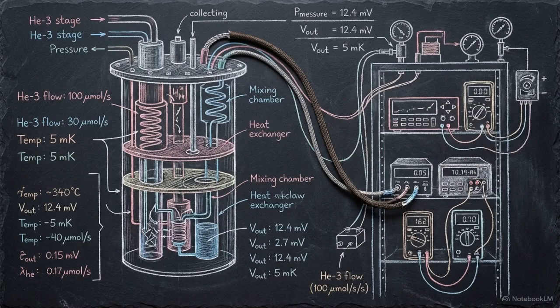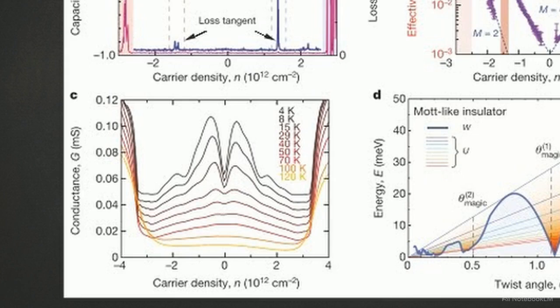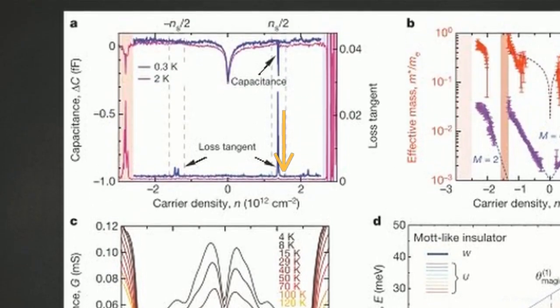Researchers proved this interaction-driven phase exists by measuring the material's response without an external magnetic field. This data shows electrical conductance versus carrier density. Panel C reveals deep valleys in conductance at the plus or minus 1.4 marks, which align with the half-filling density. Simultaneously, Panel A shows spikes in energy dissipation and dips in capacitance at those same density thresholds. These synchronized anomalies provide the proof. The pristine conductor is now an interaction-driven insulator.